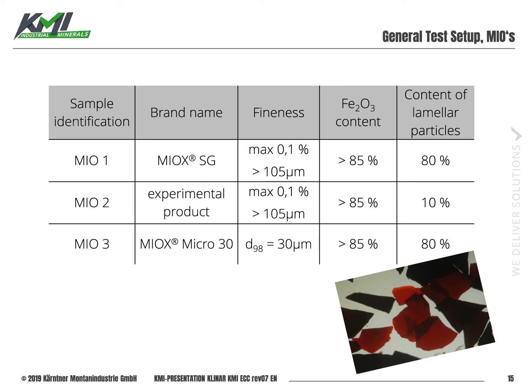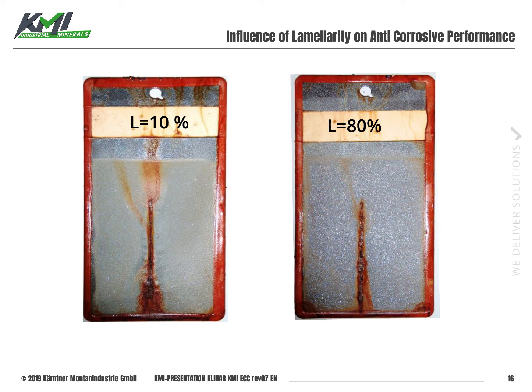A few words about the micaceous iron oxide products we tested. We tested our standard grade Miox SG, which has a content of lamellar particles of 80%, which is the most crucial quality criterion regarding the performance. Then we tested an experimental product with the same particle size distribution, but only 10% lamellas. That means it's more or less a granular iron oxide, which you can also find on the market, sold as micaceous iron oxide. And the third one is one of the new grades, the Miox Micro 30, which is roughly 3 times finer than the standard grades, and the content of platelets or lamellas is also 80%.